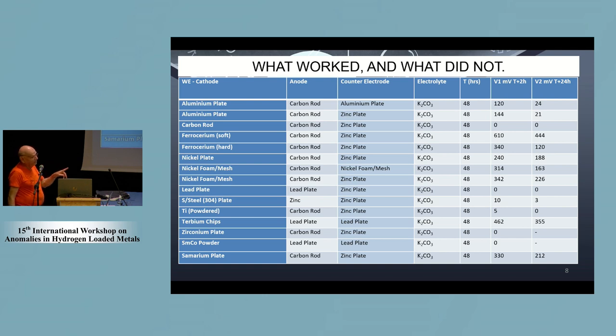Lead-lead, likewise, you see no voltage. So obviously, lead is not terribly good under these conditions at producing hydriding. To come briefly back to the kind of conditions I was using, generally speaking, I tried to get at least 1 volt of overpotential above the Faraday limit, so there was copious hydrogen production, but round about 1 watt